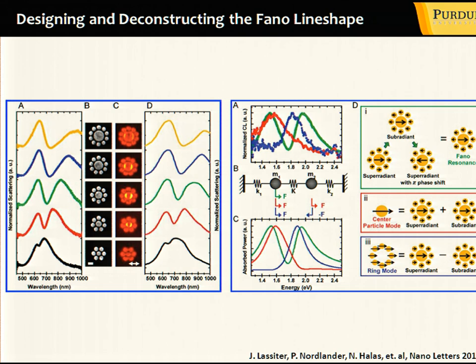It involves different modes and interference between them. But by using this E-beam, you could actually excite a particular particle in this cluster. For example, the internal one, then you would have this blue resonance, or the external one, when you have this red resonance. But when you excite it with light, then you have this Fano resonance, because you have interference between, in this case, superradiant and subradiant modes, which interfere and result in this Fano structure.